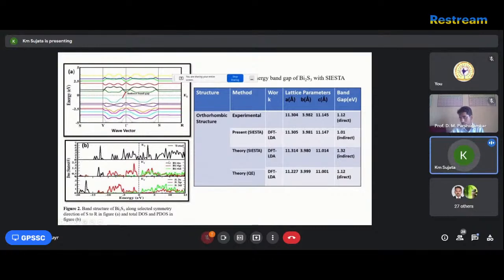This is the DOS and PDOS, meaning density of states and partial density of states. Here we see that the bismuth 6p orbitals are more dominant compared to the sulfur 3p orbitals.